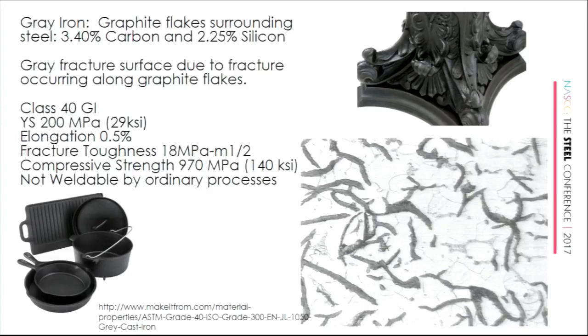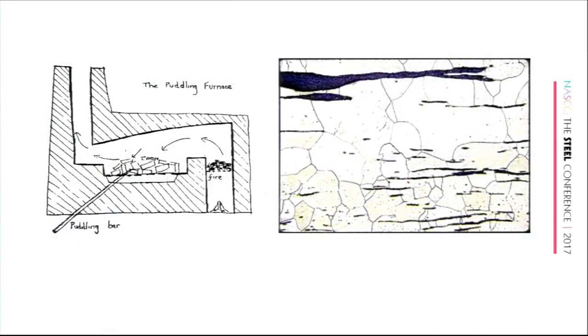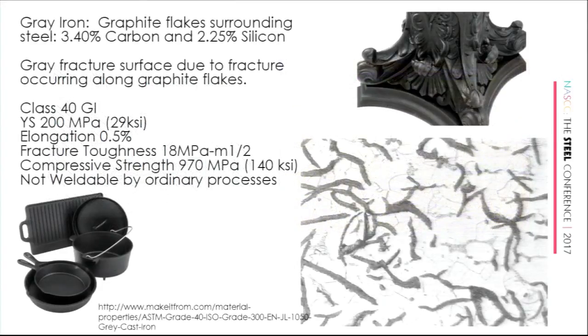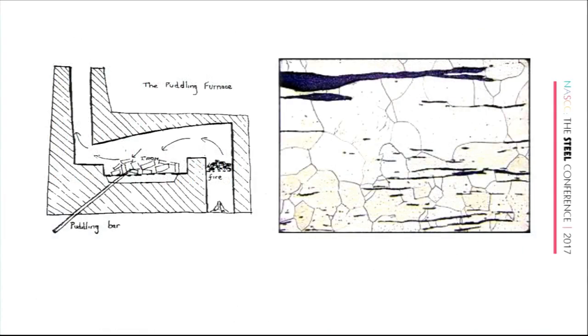But that's not the way we make steel. The way you had to make steel is you had to get rid of all this carbon. So the way you did that was you put it in a little puddling furnace and you got it as hot as you could, and you couldn't get it hot enough to melt, but you could get it hot enough to burn out all the carbon and convert all the silicon to slag. So wrought iron is basically pure iron with silica stringers, glass stringers in it.